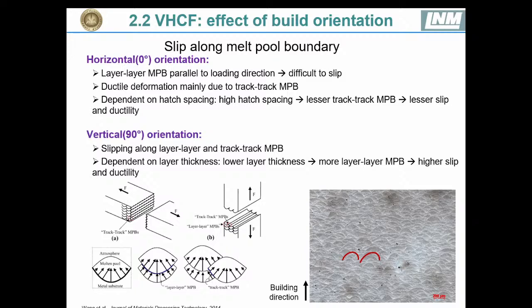Okay, and we can see when the molten pool boundary is parallel to the loading direction, then the molten pool will be difficult to slip. On the other hand, when it is vertical to the loading direction, then it will be much easier to slip. And so in this sense, for the horizontal orientation specimen, it will be much more difficult to slip, and it takes more energy, and then the strength and the fatigue strength will be increased. On the other hand, for the vertical specimen, then the fatigue strength is lower.